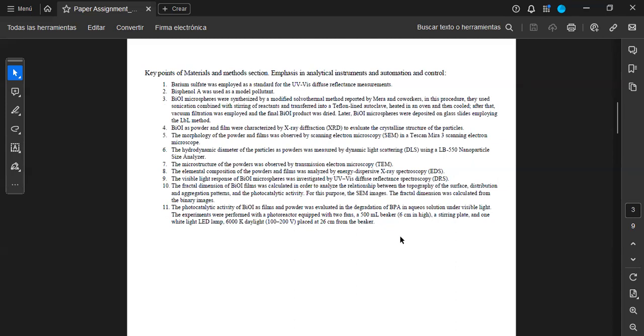Then, these BiOI as a powder and film were characterized by X-ray diffraction, and this was done to evaluate the crystalline structure of the particles. Then the morphology of the powder and films was observed by scanning electron microscopy, using the Mira 3 scanning electron microscope. After that, the hydrodynamic diameter of the particles as powders was measured by dynamic light scattering using an LB-550 nanoparticle size analyzer. After that, the microstructure of the powders was observed by transmission electron microscopy.